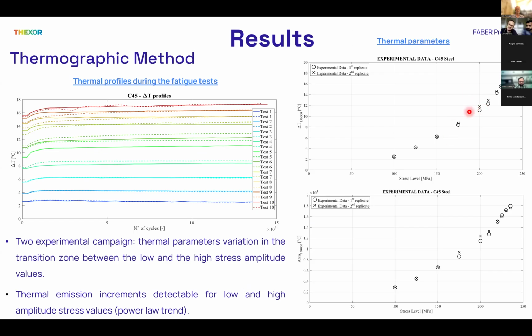The thermal parameters are not overlapped in the transition zone where the fatigue limit occurs, but you can also see this behavior in the thermal profile evolution. I would say this is a minor scatter compared to some of our results. For sure, this is awesome - we are in the transition zone where the fatigue limit is.